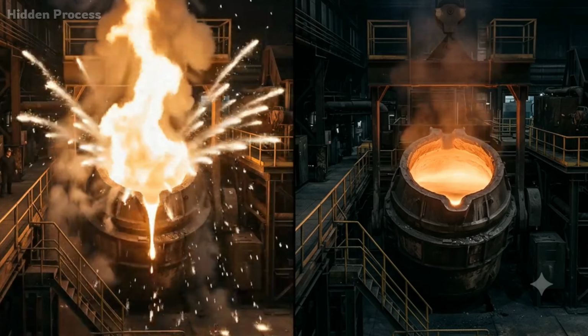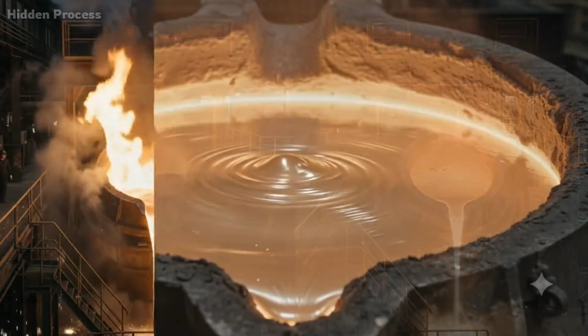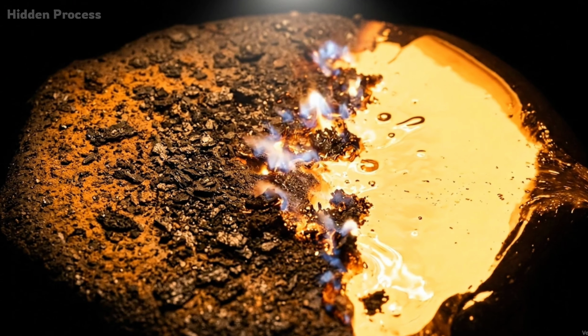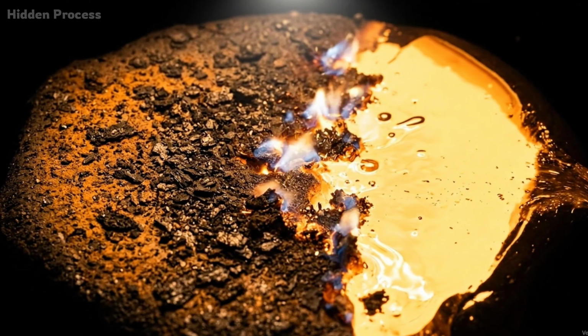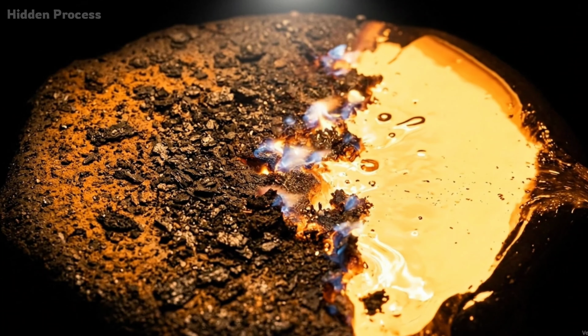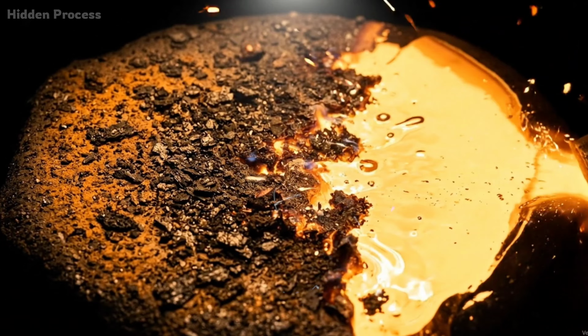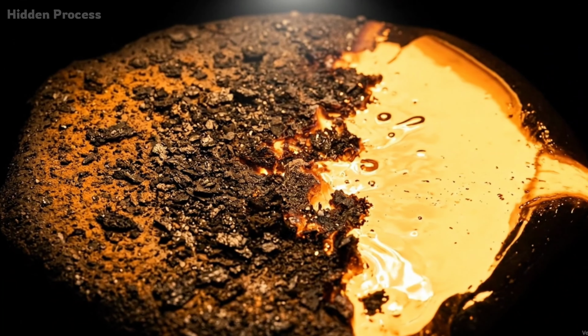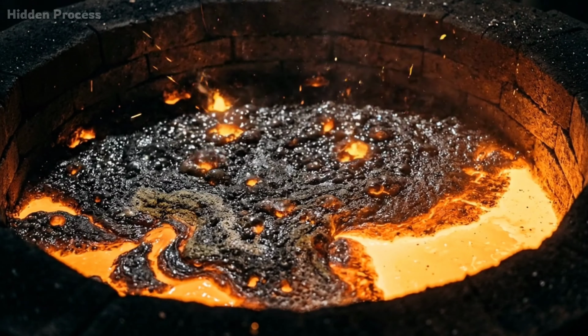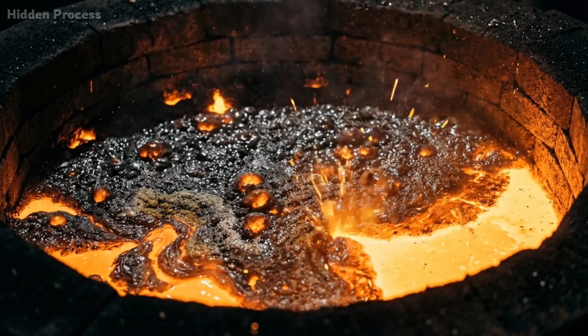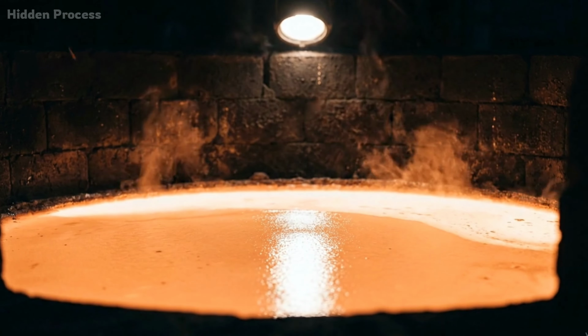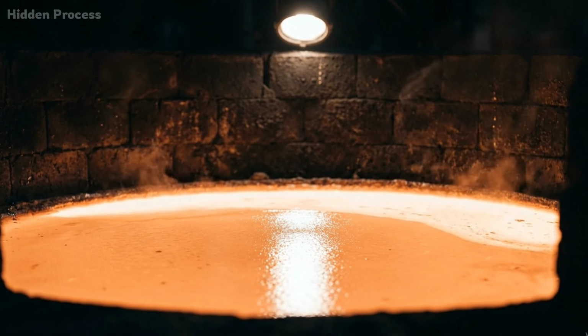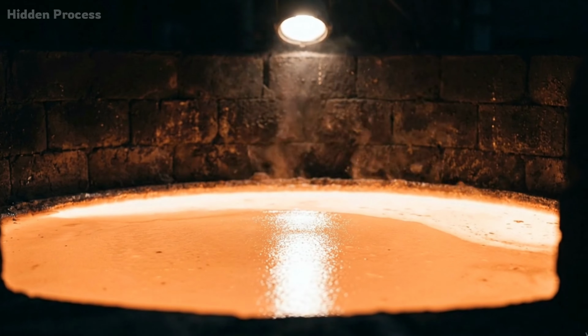In just 20 minutes, the entire chemistry of the metal changes. Carbon content drops from 4–5% down to less than 1%, sometimes as low as 0.02%, depending on the grade of steel being made. Sulfur, phosphorus, silicon, all removed or reduced. What's left is steel, still liquid, glowing, molten, but chemically transformed.